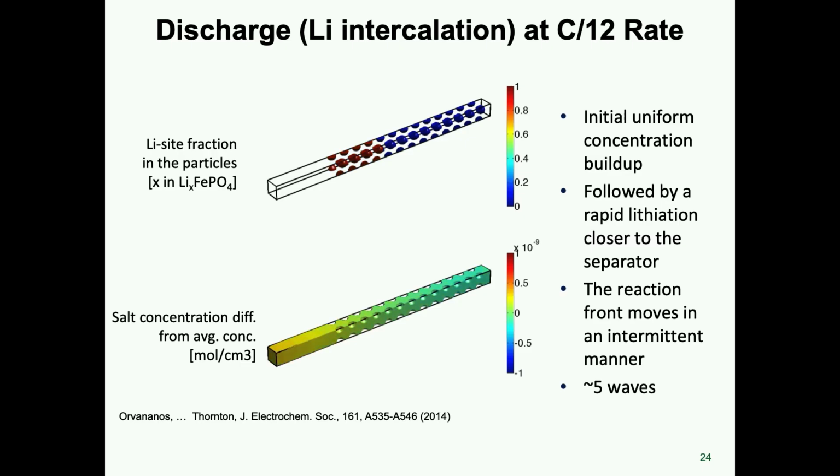So this is really complex, right? This is just all the same size particle. And you see almost like an avalanche, stick and slip type behavior. And here, we are not even looking at size distribution. So in order to actually model this system properly, you have to include both the size distribution as well as the positional distribution.